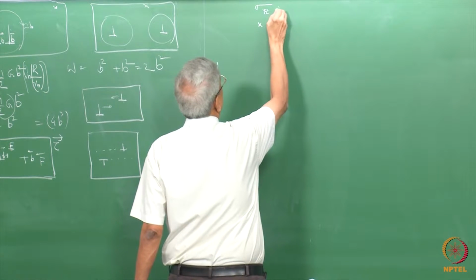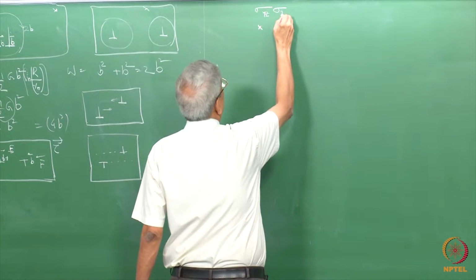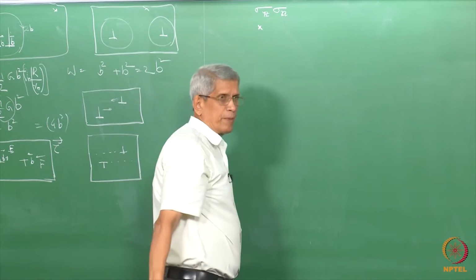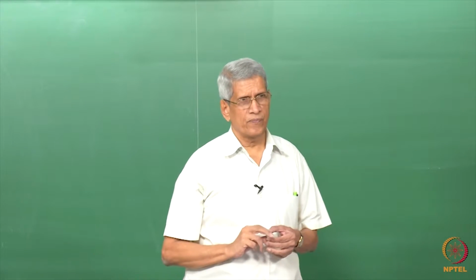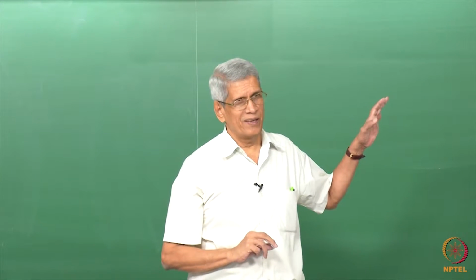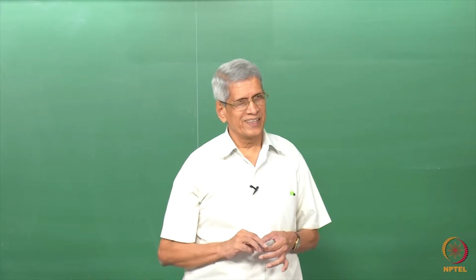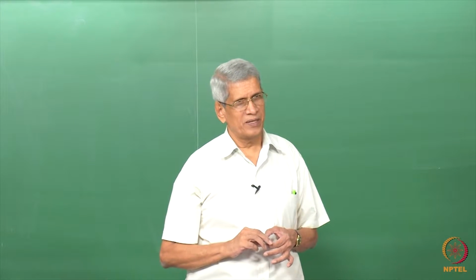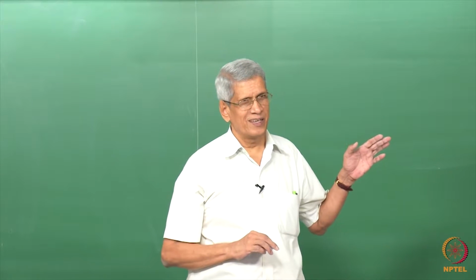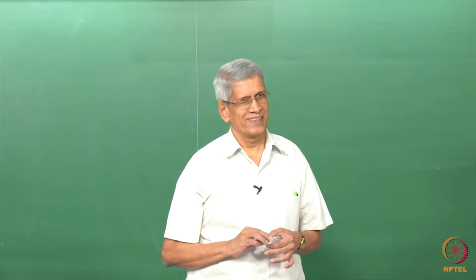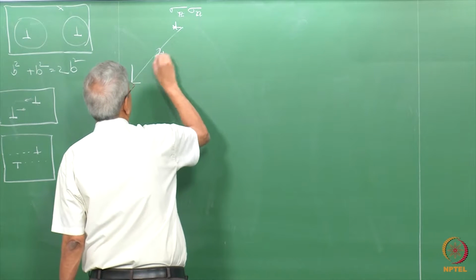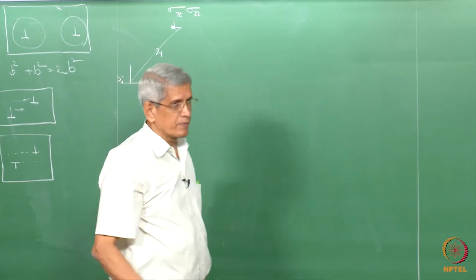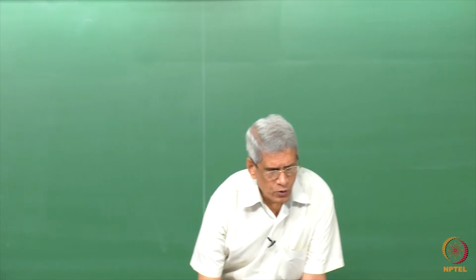Those stresses are sigma YZ and sigma XZ. These are the only stresses which are going to come, correct? And we know the Burgers vector of that dislocation, so we can find out the strain field. We can find out the energy corresponding to that at that point, and the rate of change of energy will give you the force which is acting. So that will be the force acting between the dislocations. This is the distance r between the dislocations. That is essentially what is being shown here.